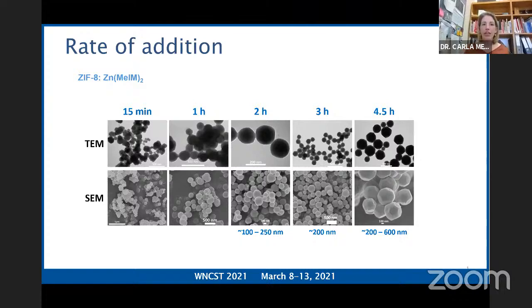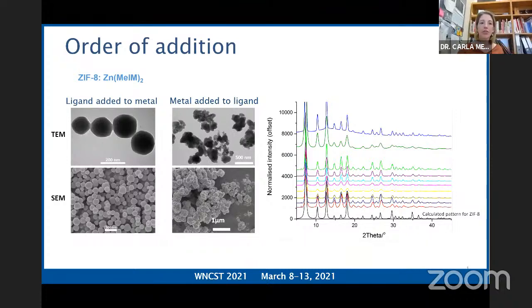So if we stick with the ZIF8 for a moment, one of the other parameters we can adjust would be the order of addition. So whether ligand is added to metal or metal is added to ligand. And here you can start to see that there's a difference in the size and the morphology of the crystals. But even though there's a distinct change in the size and the morphology, in all cases, you can see the X-ray powder diffraction pattern. The bottom here is that calculated for ZIF8, and the rest are all prepared using the microemulsion method, changing a variety of conditions, such as ligand to metal, metal to ligand, and includes the rate of addition. And in all cases, all of the resulting nanocrystals are in fact ZIF8. They all match the simulated pattern there.